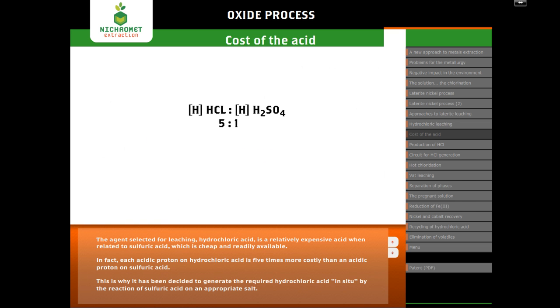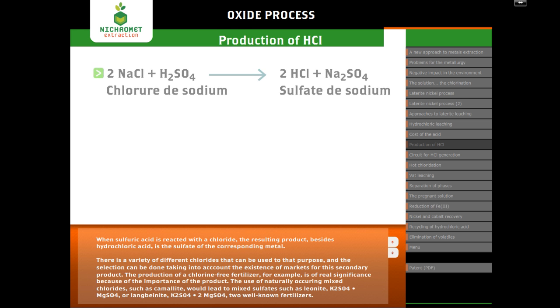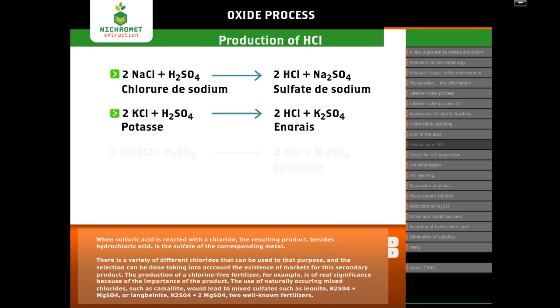The agent selected for leaching, hydrochloric acid, is a relatively expensive acid when related to sulfuric acid, which is cheap and readily available. In fact, each acidic proton on hydrochloric acid is 5 times more costly than an acidic proton on sulfuric acid. This is why it has been decided to generate the required hydrochloric acid in situ by the reaction of sulfuric acid on an appropriate salt. When sulfuric acid is reacted with a chloride, the resulting product, besides hydrochloric acid, is the sulfate of the corresponding metal. There is a variety of different chlorides that can be used to that purpose, and the selection can be done taking into account the existing markets for this secondary product.